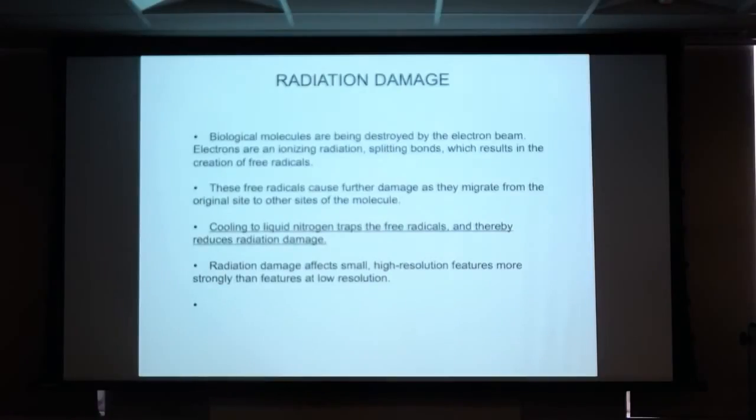So radiation damage follows from the inelastic scattering. They're being destroyed as they're exposed to the electron beam, and there are all kinds of processes like free radicals, which can cause further damage by migrating around. It's been discovered early on that by going down very strongly in temperature, we can prevent the migration of free radicals. So we can reduce the effects of radiation damage. Okay,